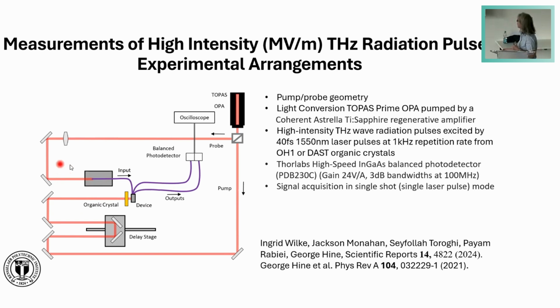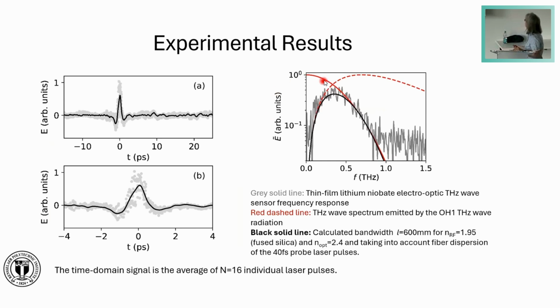Initially, they actually used a lens to couple the light into the fiber, but the laser beam drift compared to the fiber diameter was such that there were too many intensity variations when a lens was used. Then we have here the frequency spectrum, also the Fourier transform of the signal. We see a dynamic range of basically a factor of 10.